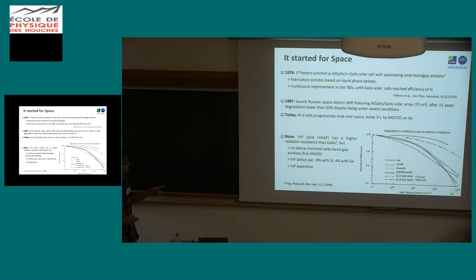It's interesting to know, just a note very quickly, that indium phosphide based materials are in general way more resilient to degradation induced by high energy particles. And here, for example, you have the efficiency degradation versus the fluence of a high energy electron beam for indium phosphide cells, and you can see it's pretty flat. Then indium gallium phosphide, then gallium arsenide, and then silicon with two different thicknesses. The worst is the thicker silicon solar cell.